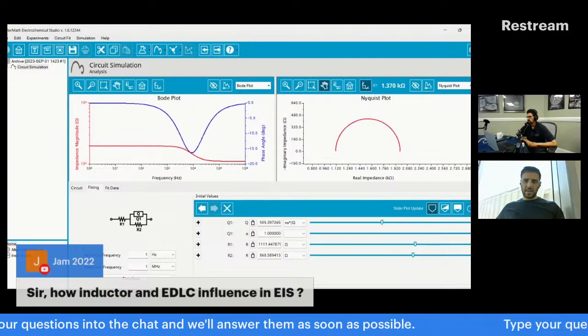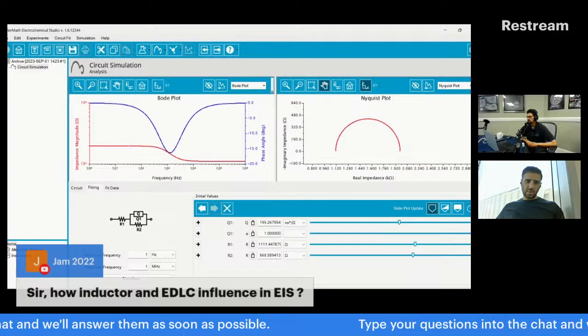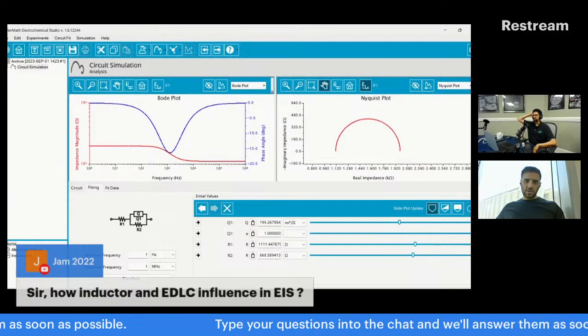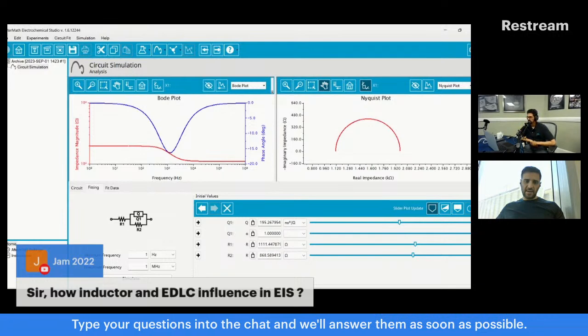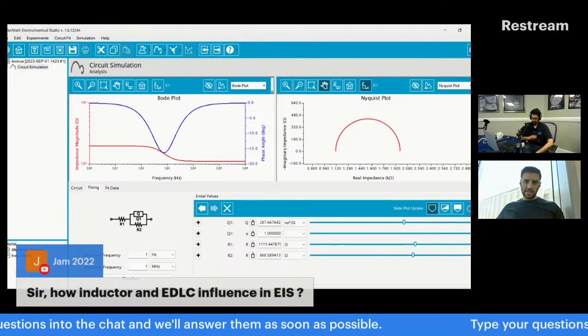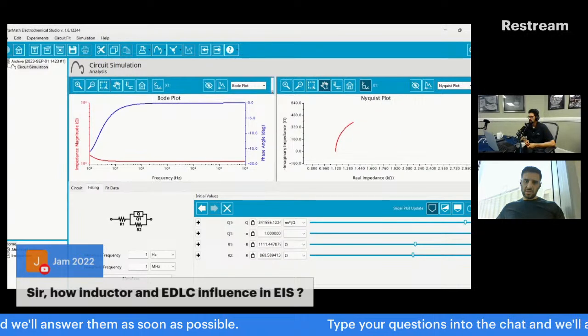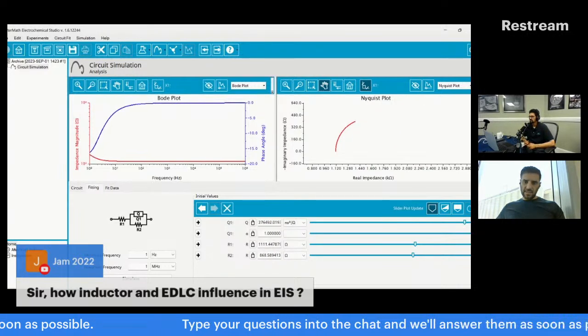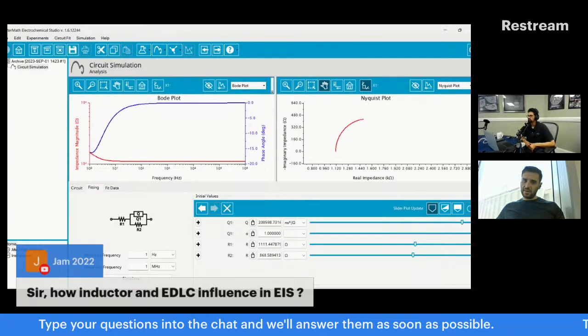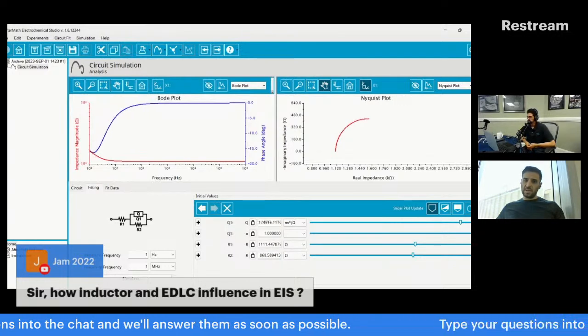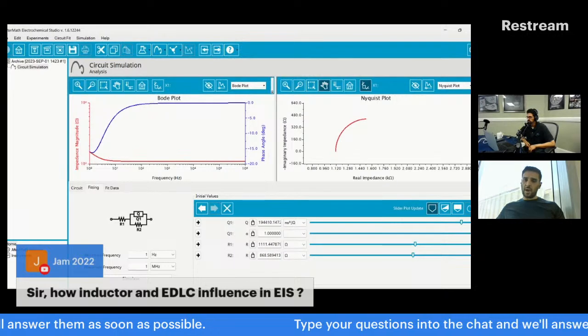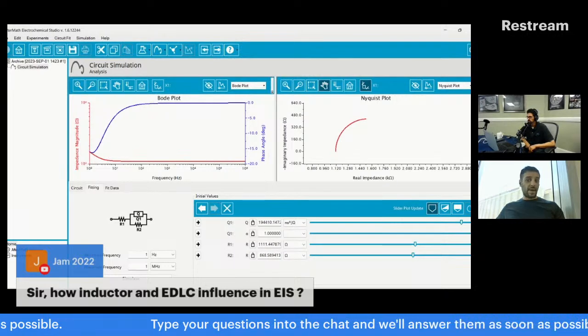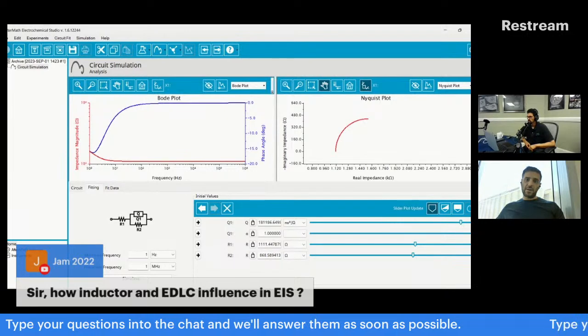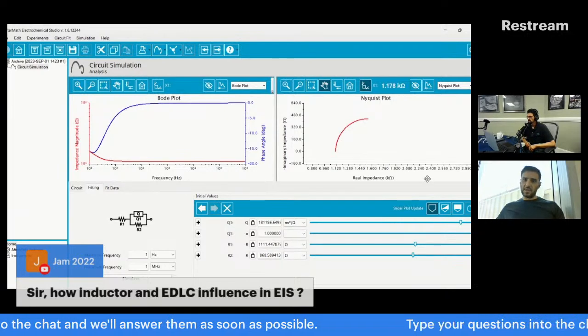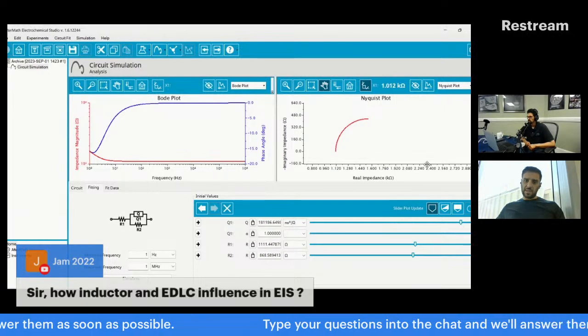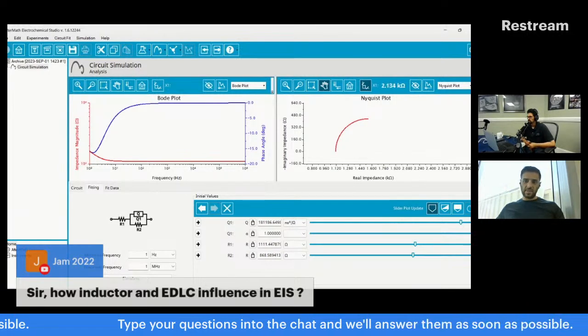You don't see anything in the Nyquist plot at least, but it changes the peak in the Bode plot. And if I go extremely high, as in I have a very, very large double layer capacitance, what you could eventually see is that the semicircle doesn't complete itself. You'd have to go to even lower frequency. This is where you start to get some ambiguity. Is it capacitance or is it diffusion? This kind of looks like a Warburg if you think about it. I know it's curved, but you can imagine something like this almost looks like a Warburg kind of element.